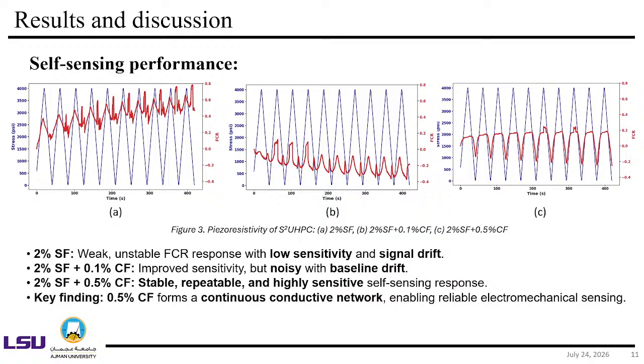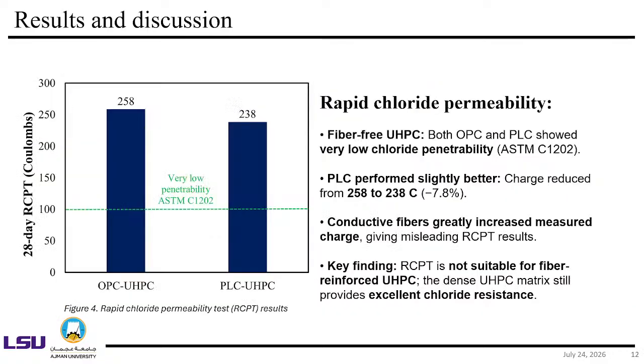And then we're looking at the self-sensing performance. From here to here, it's zero carbon fiber and more and more. It's very obvious that it's very noisy, and there is electrical signal shifting in that. That's slightly better, but still shifting. That's the best. So we can see that the 2% steel fiber plus 0.5% carbon fiber have formed a continuous conductive network, enabling reliable electromechanical sensing.